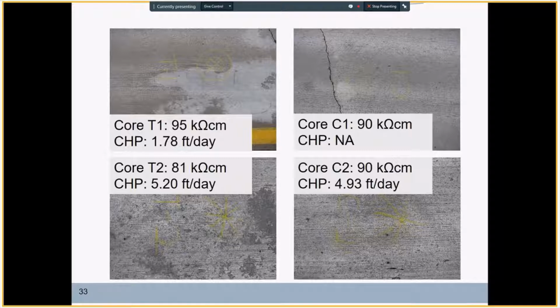We took the cores back to the lab and cured them in water for a couple of weeks to ensure they'd be responsive to resistivity measurements. Resistivity testing showed comparable data, somewhere between 80 to 90, 95 kilo ohm cm for the cores. On the day of coring, we also tried to check the permeability of the base layer, doing a core hole permeability test, finding low permeability at the base in the main crack location. For one of the control locations, we couldn't complete the test because we couldn't get stable readings.